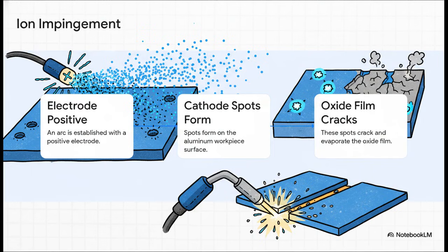So here's what's happening on a microscopic level. It's pretty cool. When that electrode is positive, a stream of charged particles, or ions, literally bombards the surface of the aluminum. It's this thing called ion impingement, and it acts like a tiny, high-powered sandblaster. It just cracks and vaporizes that oxide layer right in front of your weld puddle, clearing a path for the clean metal to join together.